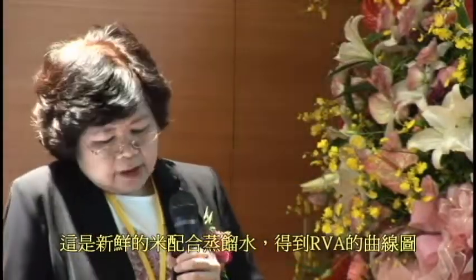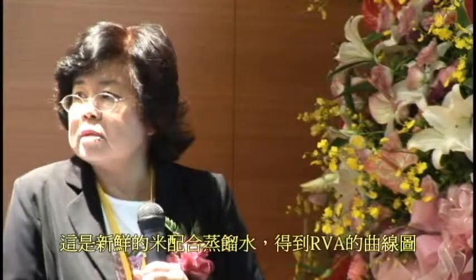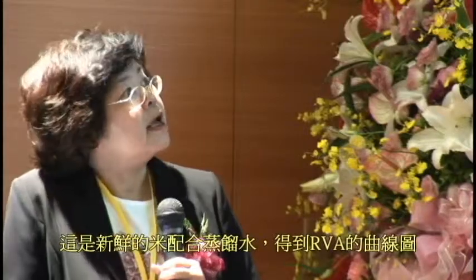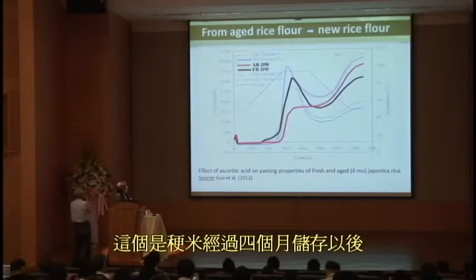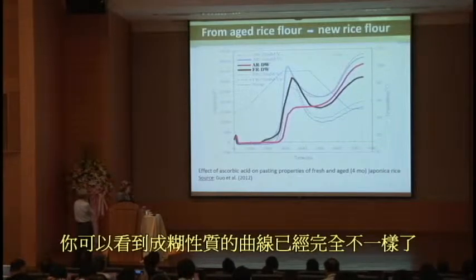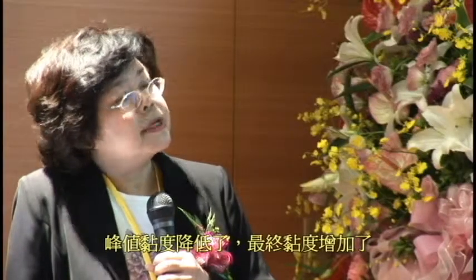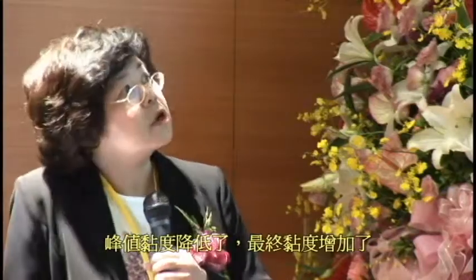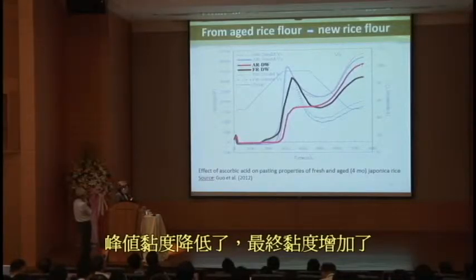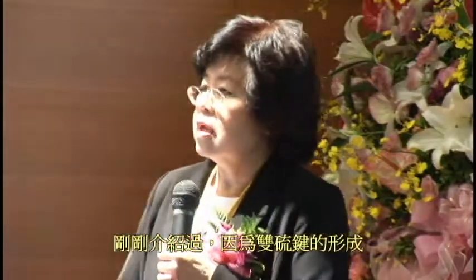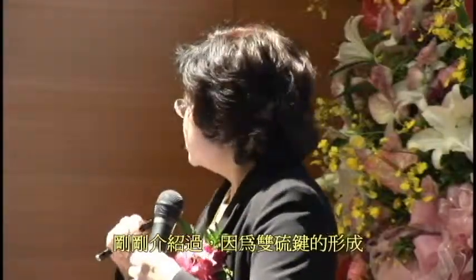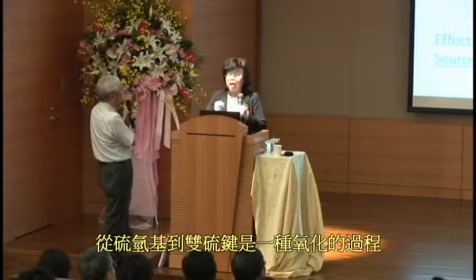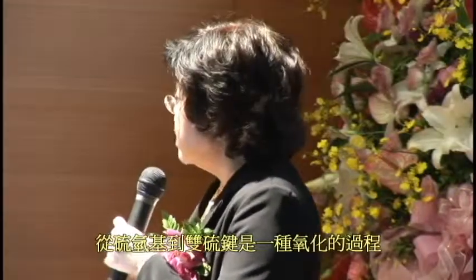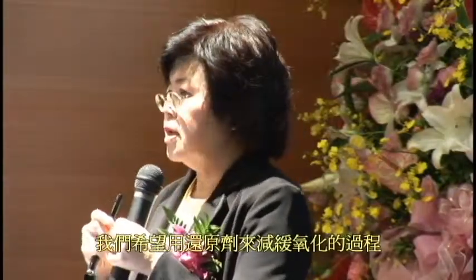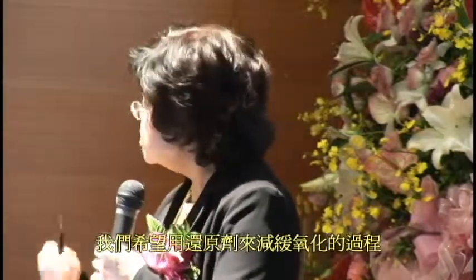This one, FR, is the fresh rice in distilled water, and they ran the RVA and got this pasting profile. And this one is for the aged rice, 4 months. You can see the change in the pasting properties: the peak viscosity is lower, and there is an increase in the setback and the final viscosity. They think it's because of the disulfide bond of the protein. And they say that the formation of disulfide bonds is an oxidation process. So they tried to use a reducing agent put into the water.